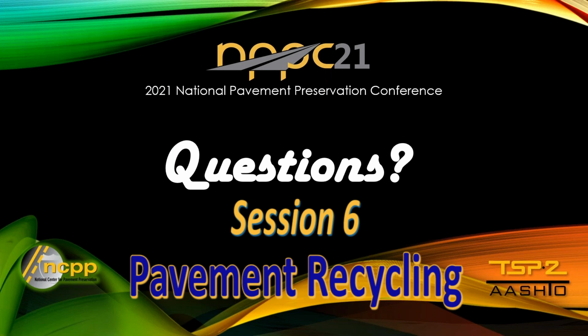I think in general, best practices still apply, especially with the CIR. And it's important to remember, depending on when you're doing your turn or your flip and you're coming back and working that joint, that material still might have a little bit of opportunity to gain density in it. So I think your best practices are very similar. Now, there are some nuances with the material, like we're not turning the temperature on at the screed, and trying to understand the fluff of material. So when you're doing CIR, let's say on a 2-lane road, the contractor needs to be conscious of the head of material in that joint, because when he comes back and matches it, there's a little bit of fluff with the CIR. So I know that's one area that an experienced contractor can really make or break performance and constructability.